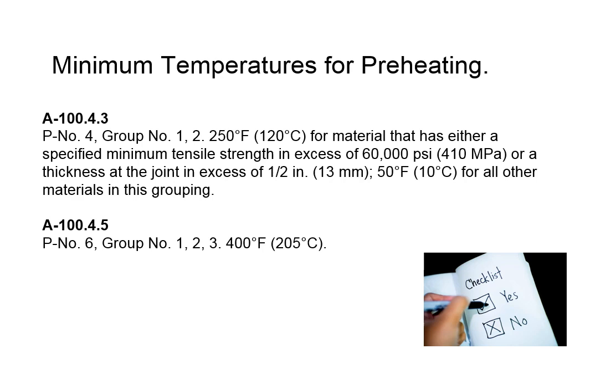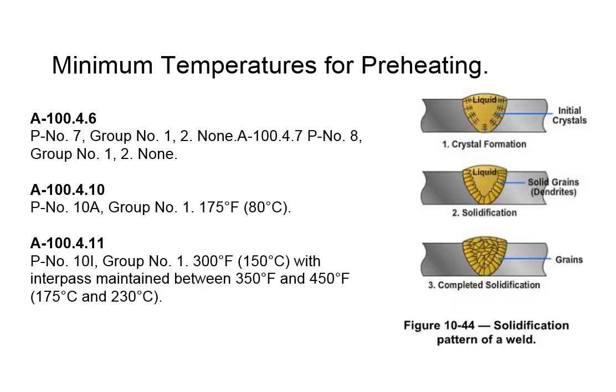Group 6, or P6, needs 400 degrees F before you even start. So that's telling you that this stuff is pretty tricky to deal with. Here's some other materials. P7 and P8. P8 is your garden variety austenitic stainless steels. You don't preheat them. You'll mess those up if you preheat them too much. And then the P-number 10A and these guys, they all get a little bit of preheat and an interpass.